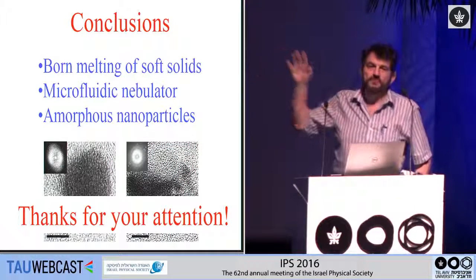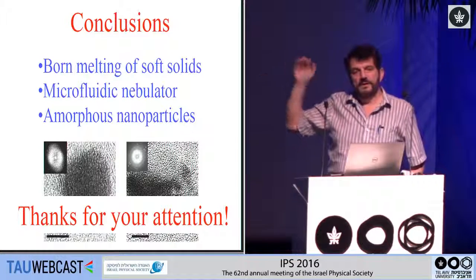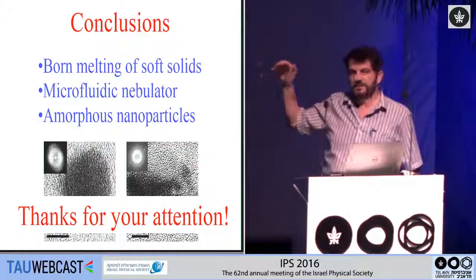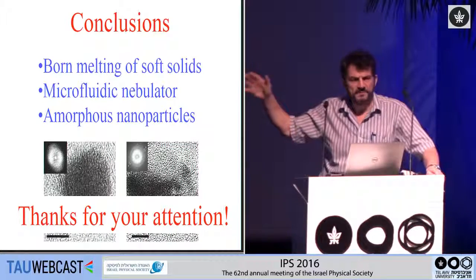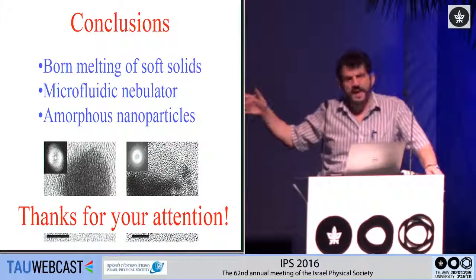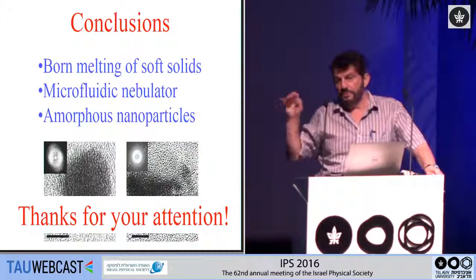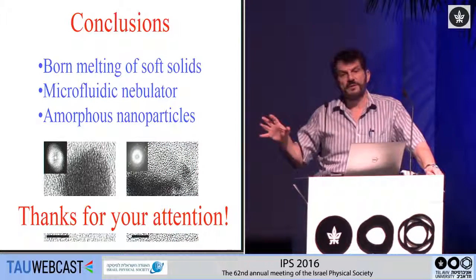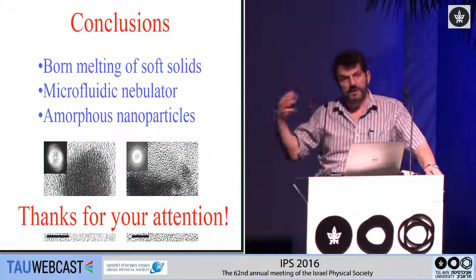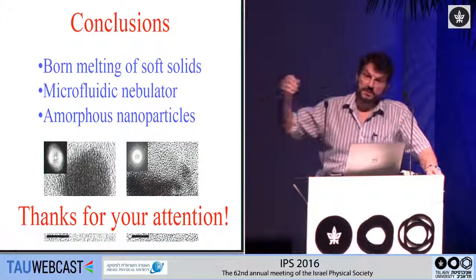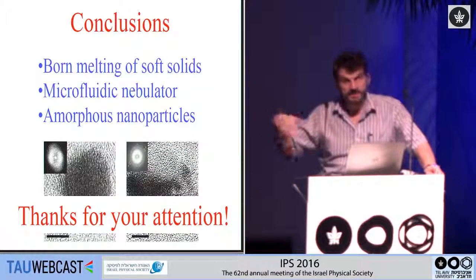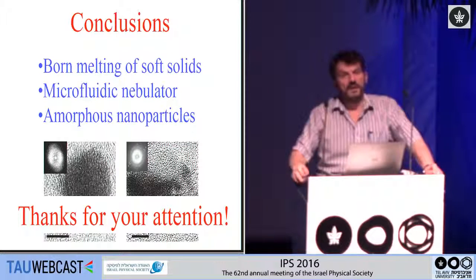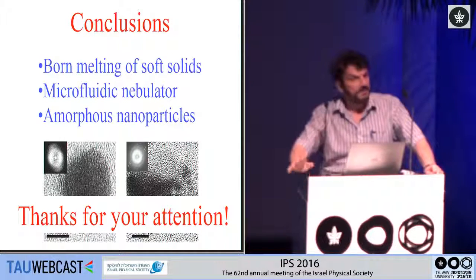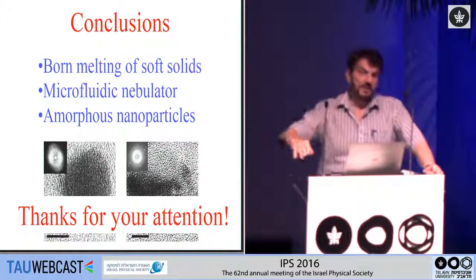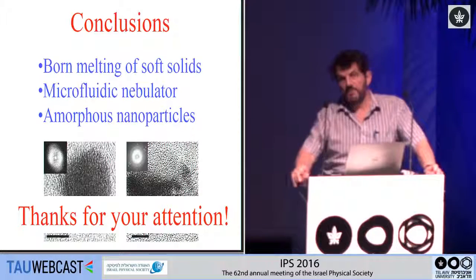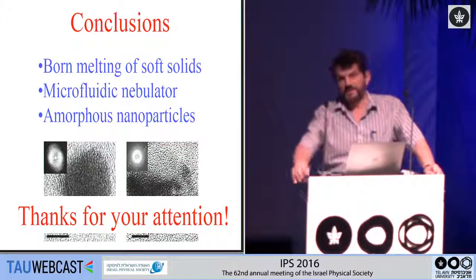I actually showed you 4 examples of generic hydrophobic drugs, fenofibrate, clemizole, and I forget what the others are, but we've done several examples of these things. And we always work, when we're trying to do this, in the situation where we can keep everything amorphous. So if we go to small enough particles, we of course have to stabilize the particles, so you have to put some coating on them to keep them stable once they're formed so they don't coalesce. But then you can keep the whole system amorphous. So we haven't looked at the case where some is amorphous and some is crystalline. But when we do make it amorphous, then it is very soluble.